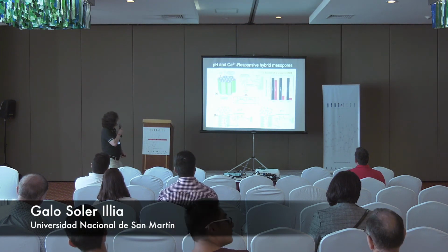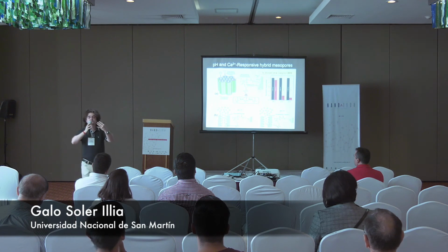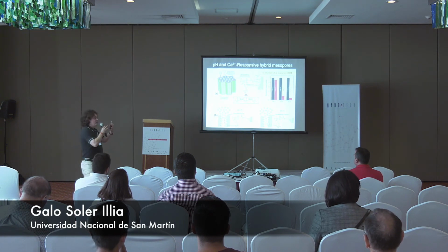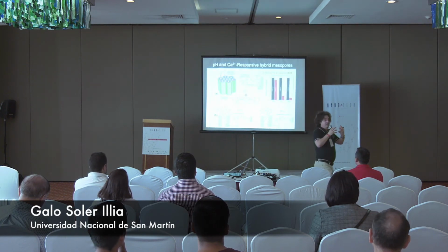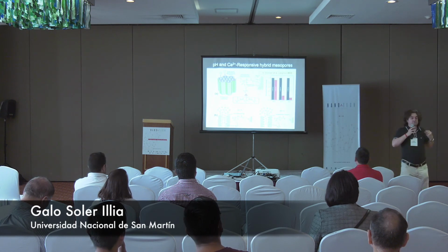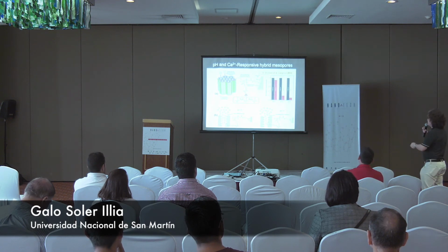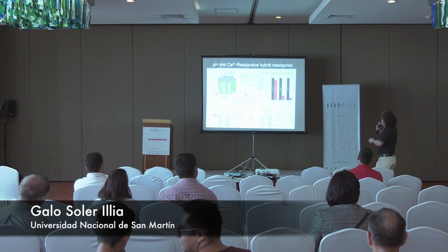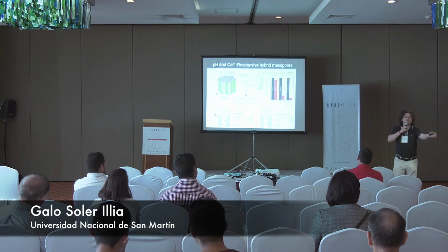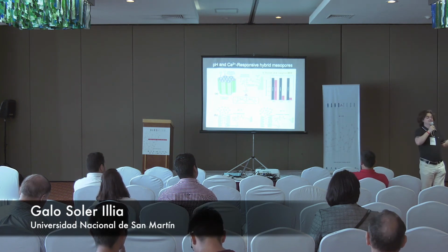Just a couple of examples to close. This is very nice. We put a phosphate polymer, and what happens with this polymer? It's a barrier towards negatively charged molecules at neutral pH. Why? Because it's phosphate. It gets ionized. So the pore is negative, and negatively charged probes do not cross the pore. But when we add calcium at neutral or alkaline pH, suddenly molecules pass. Why? Because calcium neutralizes the phosphate here, the polymer collapses and it opens.